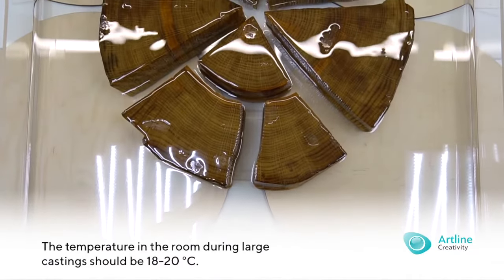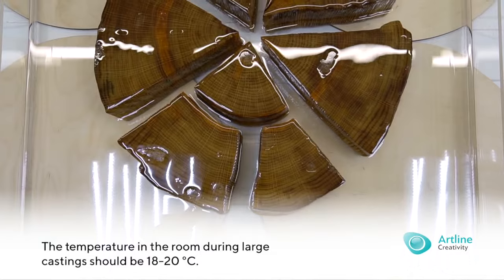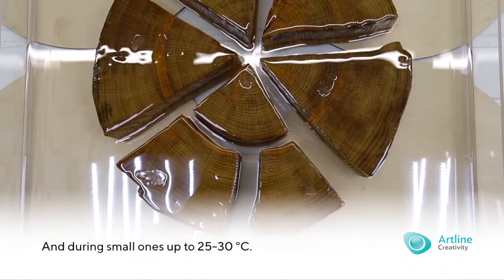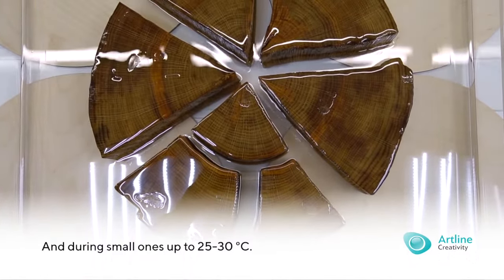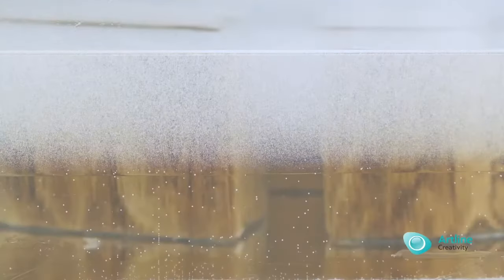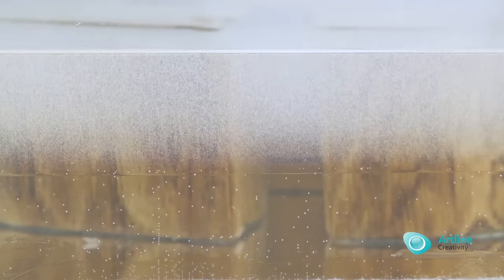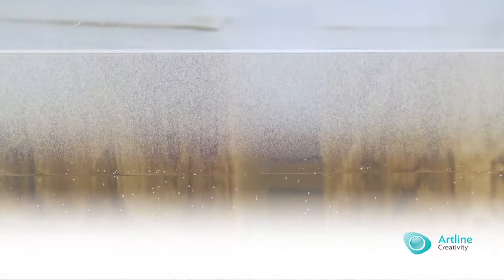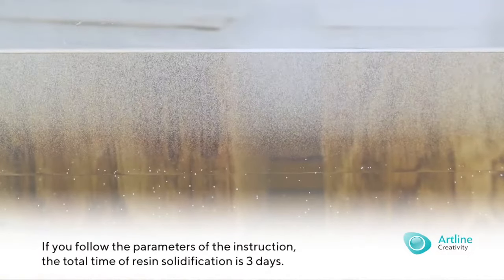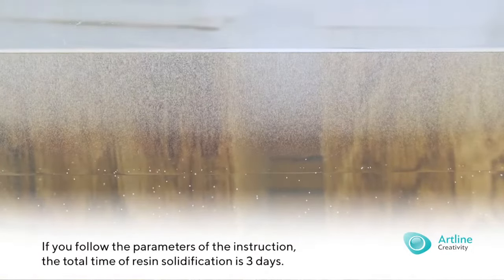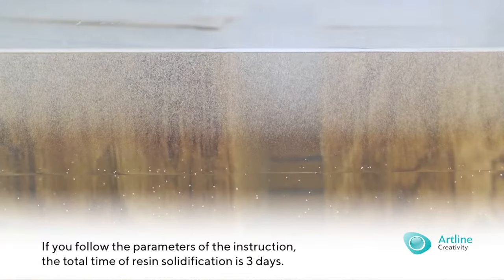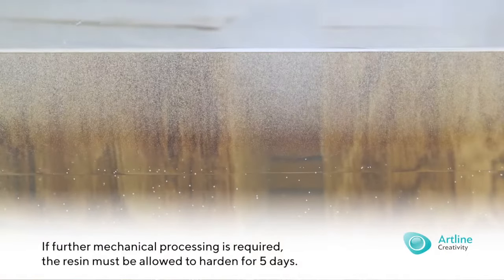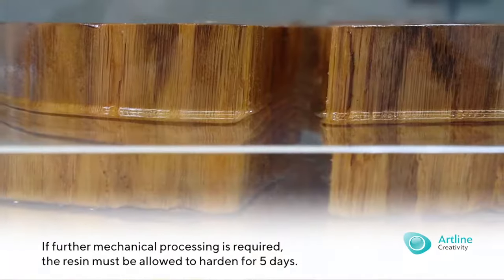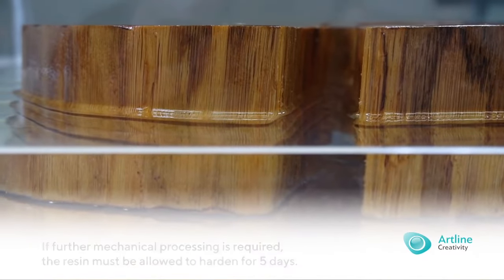When the process begins, the heat must be sufficient, but without exceeding the pre-boiling temperature and, of course, the boiling temperature. In addition, if your formwork is made of dense materials that quickly remove heat, it must be insulated after casting. Otherwise, if the temperature differs, at the points where the resin comes into contact with the formwork, gas hydrogen is formed in the form of small air bubbles.